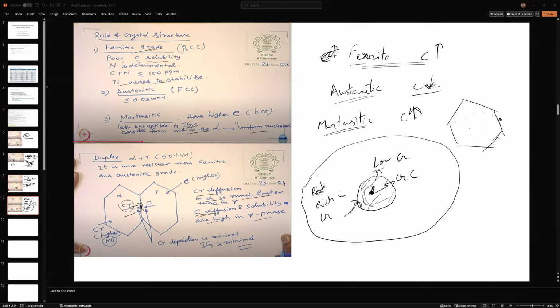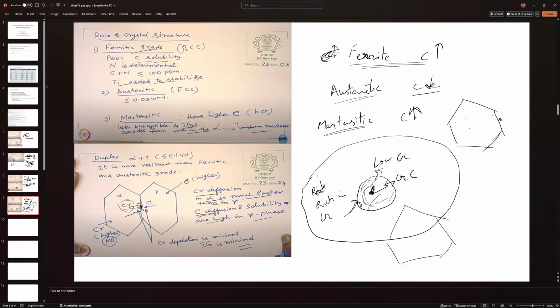Okay. Chromium content. So chromium content doesn't matter, since near the grain boundary, even if you increase the initial chromium concentration, you'll still deplete chromium due to formation of carbide. So you'll still get chromium carbide. Doesn't help much. If chromium carbide is not present in the grain boundary, it doesn't matter. Chromium depletion does not occur at grain boundary.